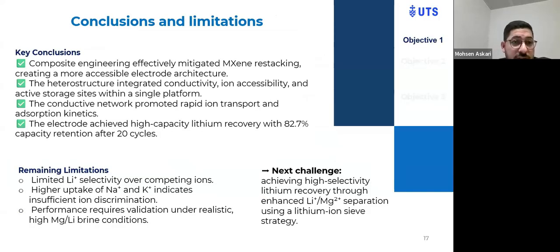The conclusion of this chapter was that the composite engineering effectively mitigated the MXene restacking, creating a more accessible electrode architecture, and the heterostructure integrated conductivity, ion accessibility, and active storage sites within a single platform. The conductive network promoted rapid ion transport and adsorption kinetics, and the electrode achieved high capacity lithium recovery with 82.7% capacity retention after 20 cycles.